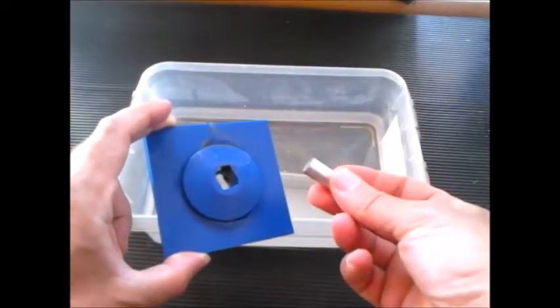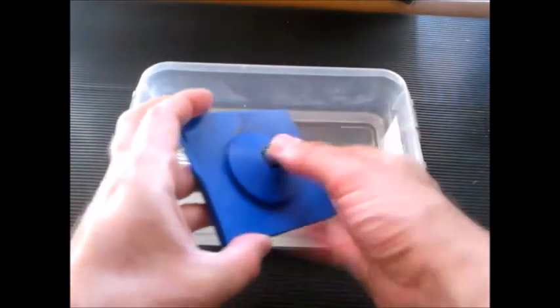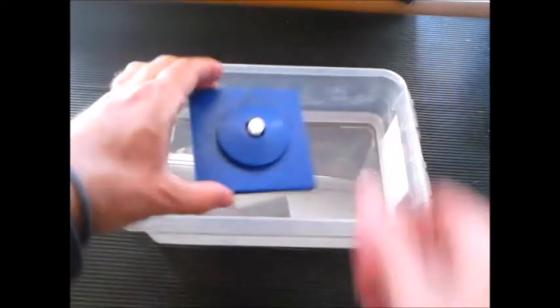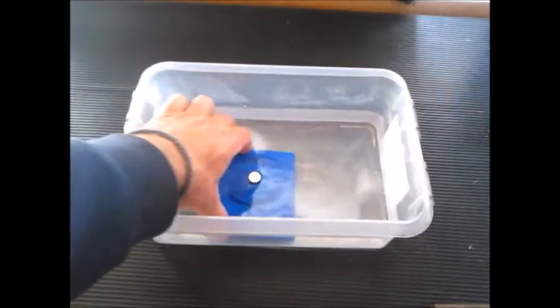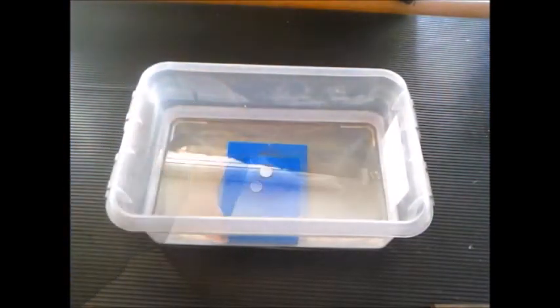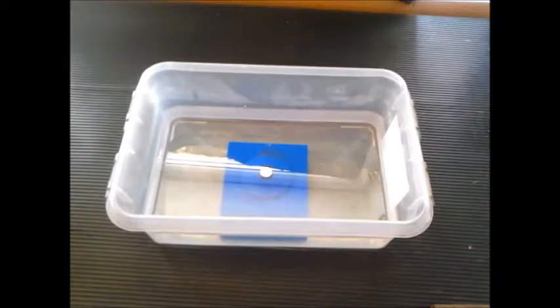The sample is fixed in the sample holder and put into the electrolyte. We usually used tap water. The temperature was held constant at around 20 degrees Celsius plus minus 1 degree. We also tested in distilled water, seawater, acids and other liquids. The used liquid has a big influence on the final erosion, since chemical effects will overlap with pure cavitational effects.